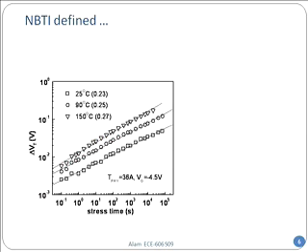Now, as I said, if you look at the delta VT, the threshold voltage shift, as a function of stress time at various temperatures, 25, 80, and 150 degrees C, then you will see that on a log-log plot, this has a straight line. I'll explain that in a second, but let me first explain what I am talking about with delta VT. Delta VT is essentially when the black curve came down to the red curve. It's because its threshold voltage changed.